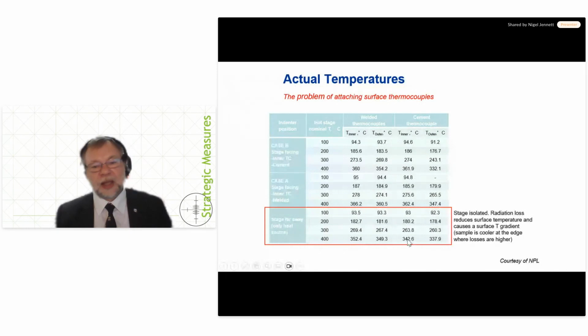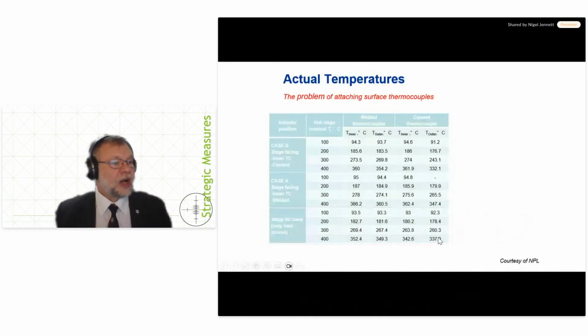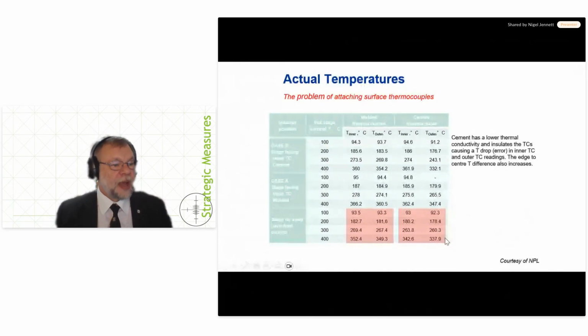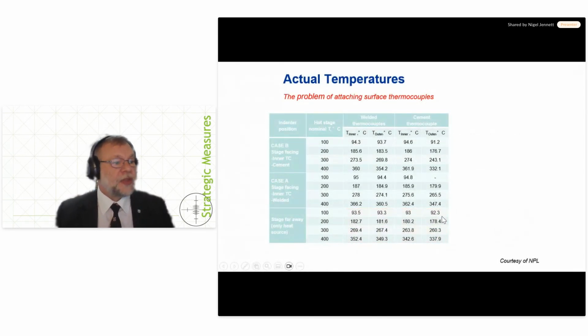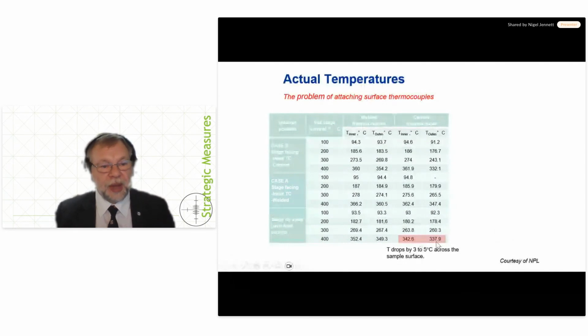If you put cement in the case, you might have 340, but you'll be indenting into the steel. So you've got a 10-degree error there already. And if you're looking at the edge, you might have 330 because you're actually measuring an indenter in the surface at the center. So you've got 20 degrees or something like that difference there. If you start looking at what happens if you put cement, you can see that there is a problem with the T-drop being larger even across the surface just using the cement. So strange things are happening.